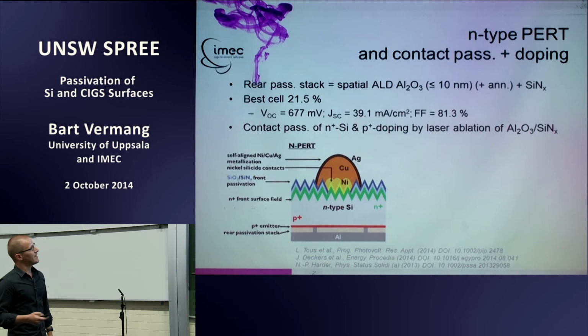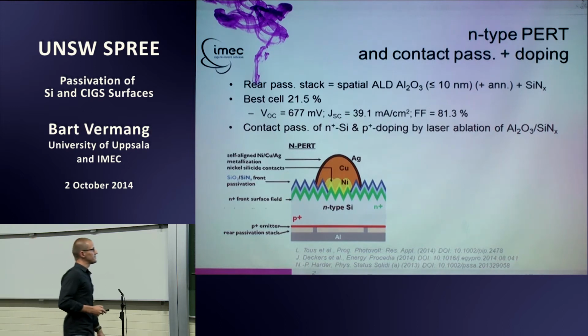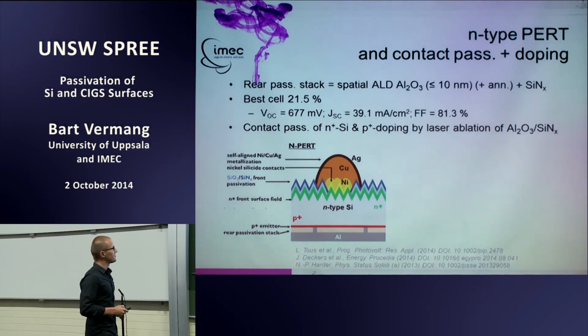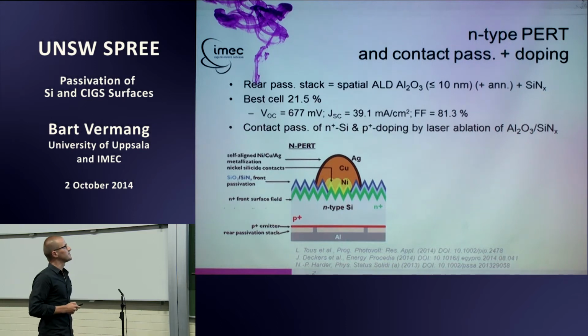So in the meanwhile, IMEC started to work on N-type PERT. In the end, they're using a very similar passivation stack. So N-type PERT is just, you have a totally diffused layer at the rear, which is now a P+ layer. So it's a bit more highly doped. However, they're using the same passivation layer, and they're really reaching high efficiencies. So the best efficiency for the moment is 21.5%. Again, a large area, decent VOC and other characteristics.